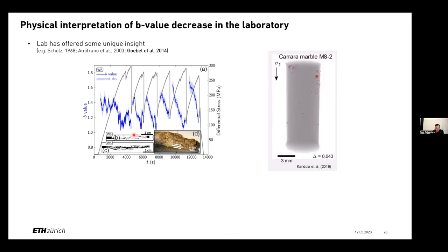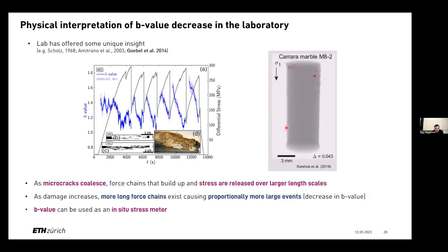What are the physics behind this? We're starting to paint a nicer picture, and what I'm showing here on the right is a video from the X-ray dynamic XRCT. In this video, what you're seeing in red is higher porosity, and they're loading the sample. As this number decreases, the differential stress is increasing, and you'll see this coalescing of damage, which is associated with the increase of porosity, or the coalescing of smaller cracks to bigger cracks, or the formation of new smaller cracks, which provides longer force chains. And you see the shear fracture that's developed. One of the hypotheses here is that microcracks coalesce, force chains build up, and then when they do release stress, it's over a larger length scale. Therefore, as your samples push to failure, the proportional amount of larger events increases because there's more contiguous damage in the sample.